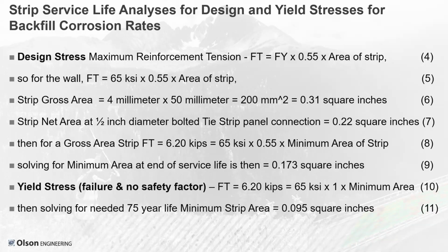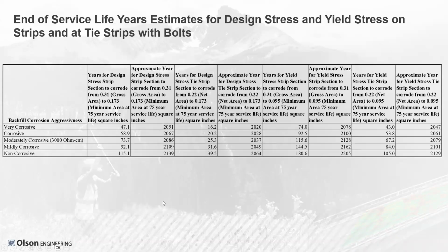So the yield stress is the failure with no safety factor. So applying these equations, then solving for that, you come up with, well, it won't start yielding until it loses about half of that amount again at 0.095 square inches. That would be the ultimate strength in a sense when it yields. So we went through those calculations to continue towards the results. I'm sure it's hard to see all this. I'll boil it down to be a little simpler, but we looked at different backfill corrosion aggressiveness states.